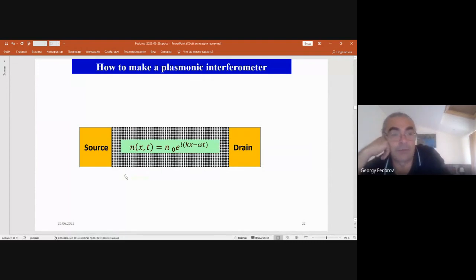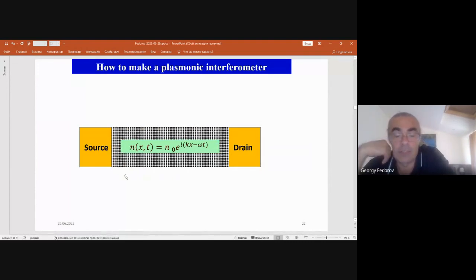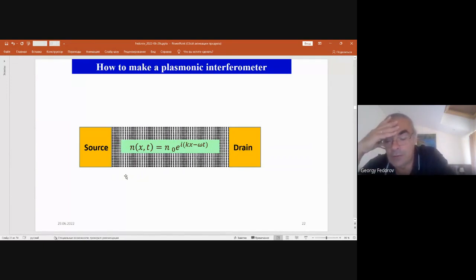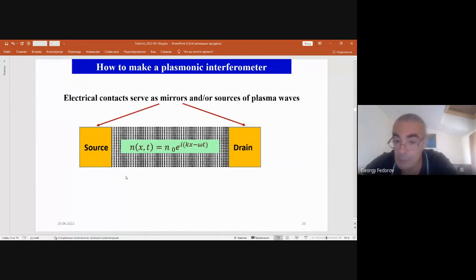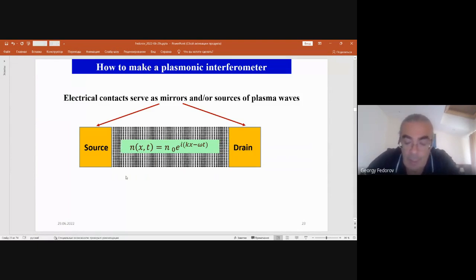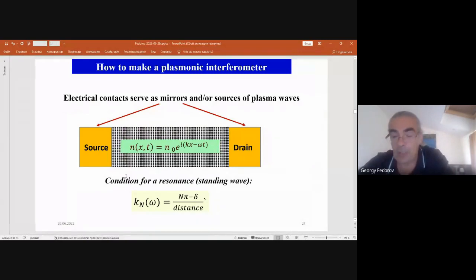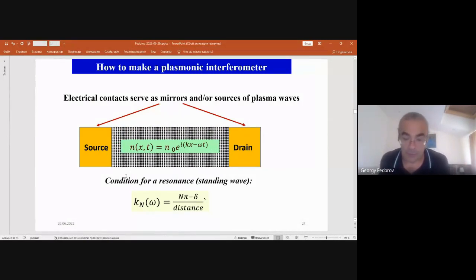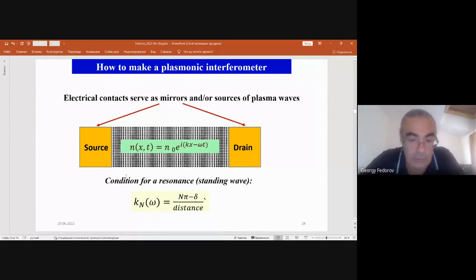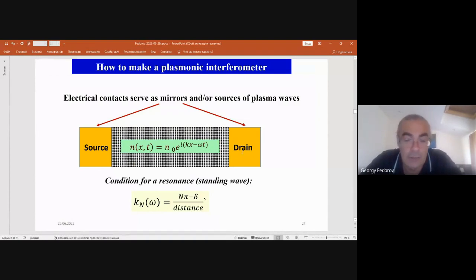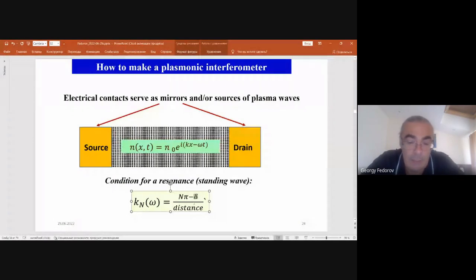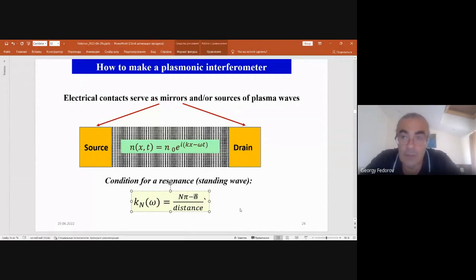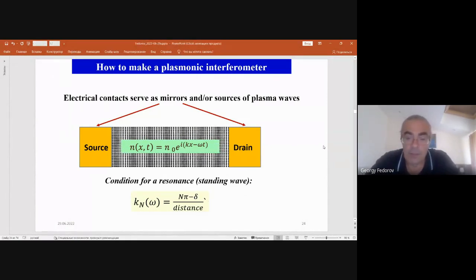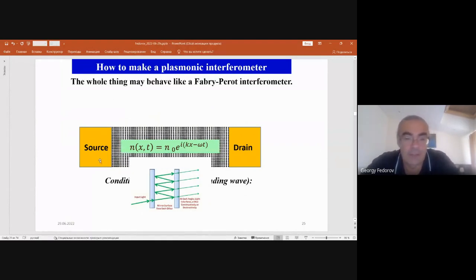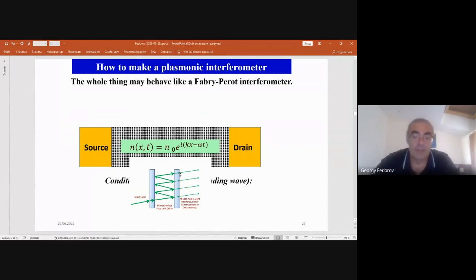So first of all, the simplest interferometer we can make is already there because we probe electrical properties of graphene. We already have these source and drain contacts that we can think of as operating as mirrors, although not very good, but still these are mirrors for plasmons. And we can obtain a standing wave here, and getting a standing wave may somehow change the properties of this device, and we have to find out how we detect this situation. But still, the condition for a standing wave is written here. Importantly, it always has some correction to the numerator, which depends on the boundary conditions and the phase that a wave acquires when reflecting from the mirror. Okay, so we can think about using this graphene channel, or any other two-dimensional channel, as a Fabry-Perot for plasmons.